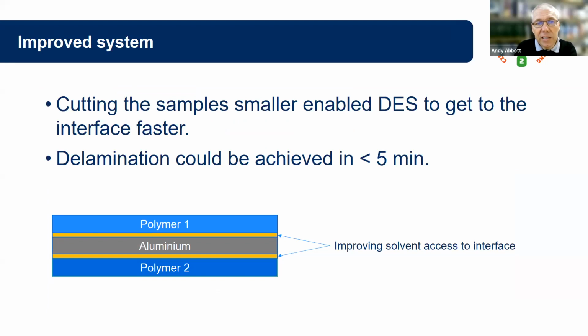Obviously, if we have a larger sample, it's harder for the material to go through the different polymer layers. But if we make the sample smaller, if we chop it into smaller samples, then we can get delamination times down to about 5 minutes, which can take us to a continuous flow process, which is clearly the advantage that we all want to have.